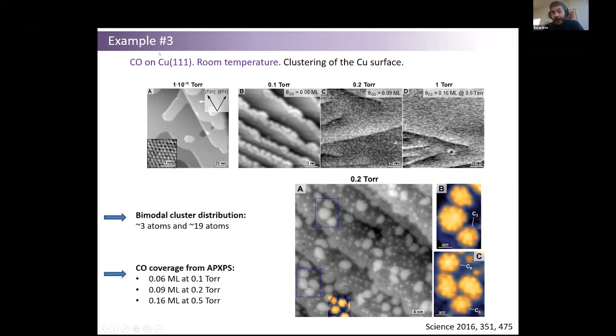And copper or gold are actually a bit special in this case because they are low cohesive energy metals. So for other metals like maybe platinum, you could maybe see this if it's energetically favorable to form, but you have to go to higher temperatures. But for copper, already at room temperature, this can happen.